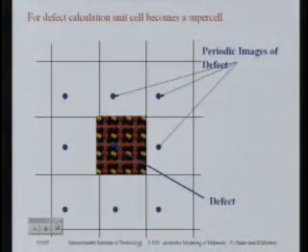So, let's say I've taken out an oxygen here. I repeat the defect so that in essence I just have a bigger unit cell, but it's one with a defect in. This is now my unit cell. Okay? And that's called a supercell approximation. So you make a cell that's big enough so that you hope that these defects don't interact.